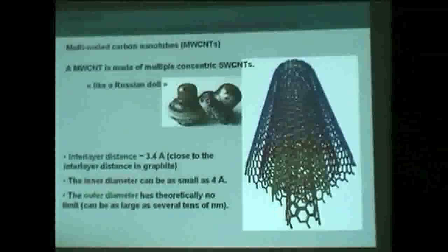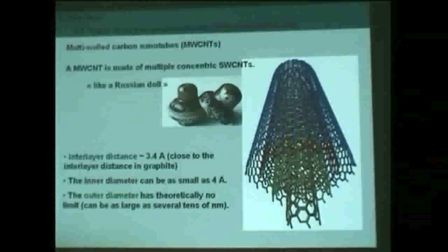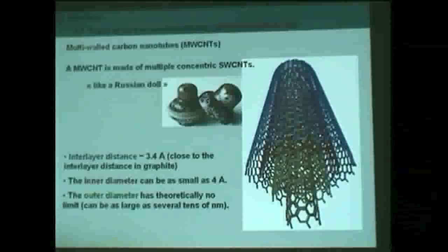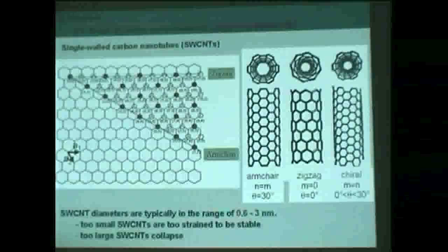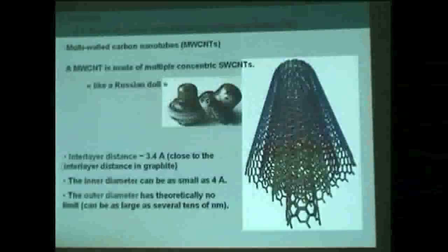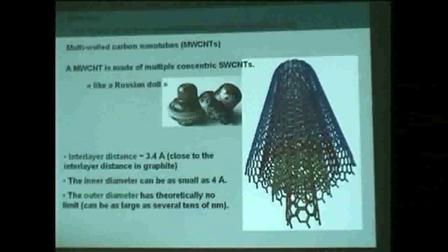In this case, the inner tube may be stabilized by the outer layers, and as a consequence, you can make smaller diameters because of this stabilization effect. So instead of having a minimum diameter of about 0.6 nanometers, there have been observations of inner tubes of multi-wall nanotubes as small as 4 angstroms, 0.4 nanometers, because of the stabilization by the outer layers.